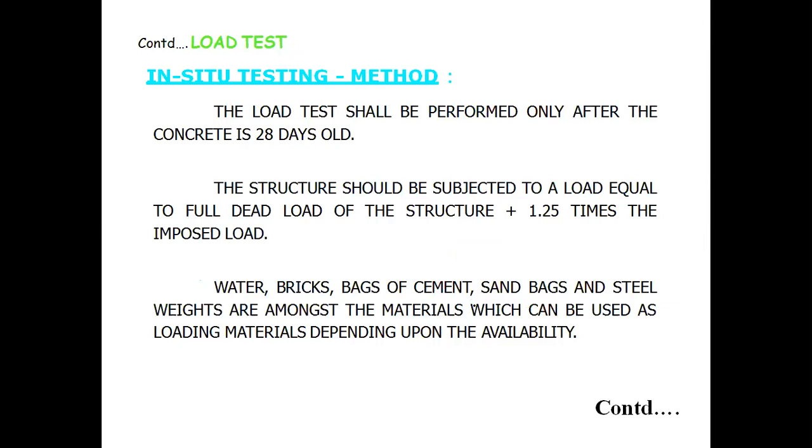So here the load test shall be performed only after the concrete has attained its characteristic compressive strength at 28 days old. Okay. And finally, the structure should be subjected to a load equal to the full dead load of the structure plus 1.25 times the imposed load. So that is how they are going to consider the total load which is acting on the structure. They will consider the full dead load of the structure along with 1.25 times the imposed load. Okay, that is very important.